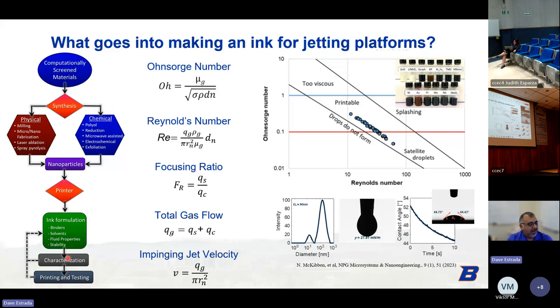And then we go into characterizing the ink, printing, and doing our test prints and reformulating as needed. What we're really targeting is tuning the relationship between the Ohnesorge number and the Reynolds number. In the Ohnesorge number, the viscosity is in the numerator, where the surface tension of the ink is under the square root in the denominator, along with the density. And then this is the nozzle diameter of the printer.